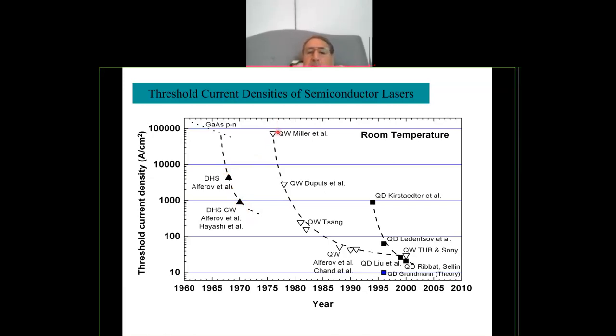So in the early 80s, when we started having MBE and making quantum wells, this is the early one where the quantum well lasers weren't very good. But look, as a function of time, within 10 years you can see the state of the art of these lasers is around 20 to 25 amps per square centimeter. So by reducing the size of the quantum structure, we have gone from nearly 1,000 to 20. Now, when quantum dots came, people managed to grow quantum dots, actually just by accident. You can see here it's now about 10 to 15 amps per square centimeter. So now they're performing even better than the quantum wire. This is why size quantization is very important, as predicted by the density of states.